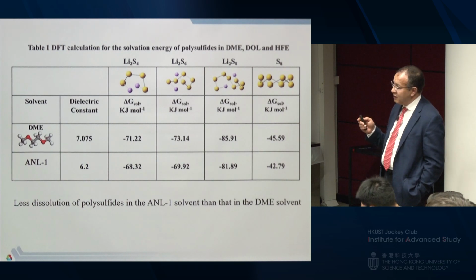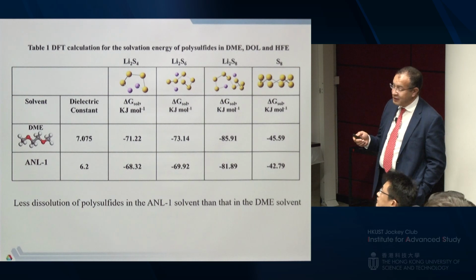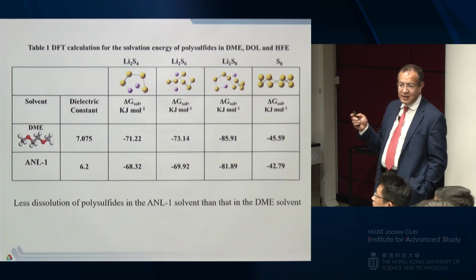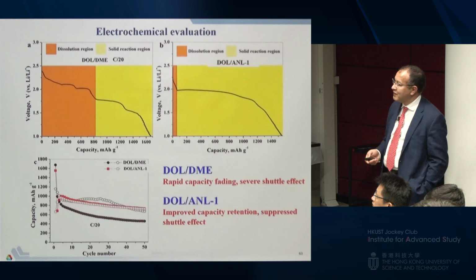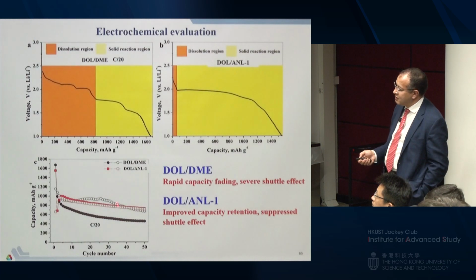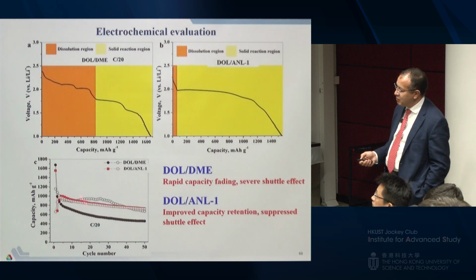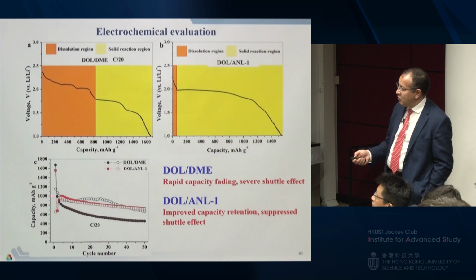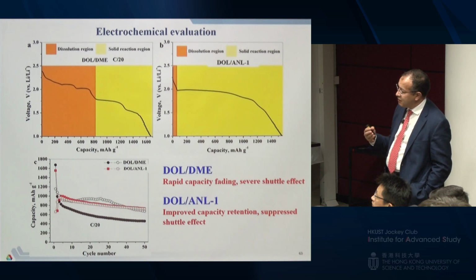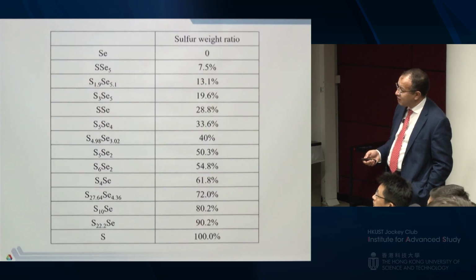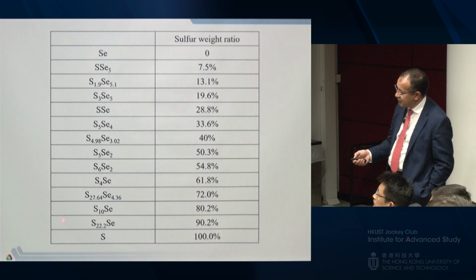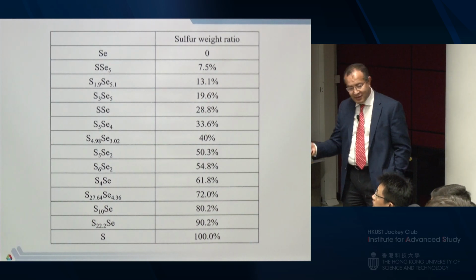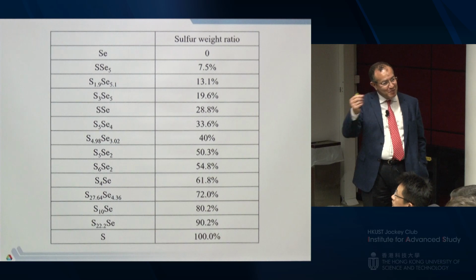So now we have a selenium-sulfur that gives us conductivity, and we have this electrolyte that prevents dissolution. So we cycled it, and you can see this is the ether base. You have a big polarization because of the shuttle effect. This one basically doesn't have any shuttle effect, and it cycled very well. Obviously, this is 5 sulfur for 1 selenium. We looked at a whole bunch of phase diagrams, and we looked at this one where we have no dopant. Selenium is really a dopant, so very small quantities.